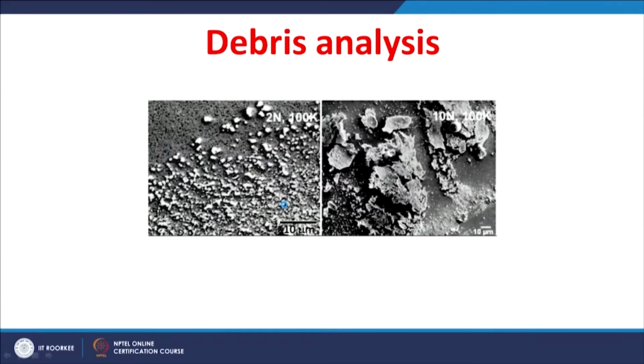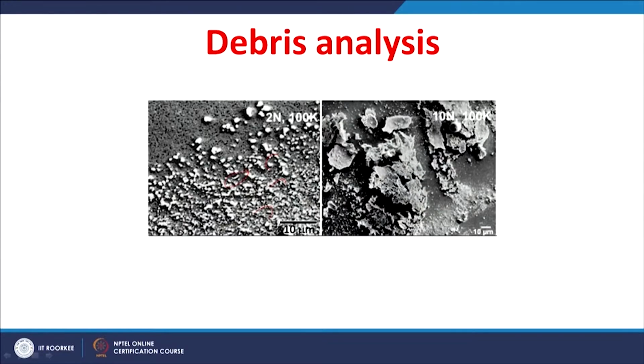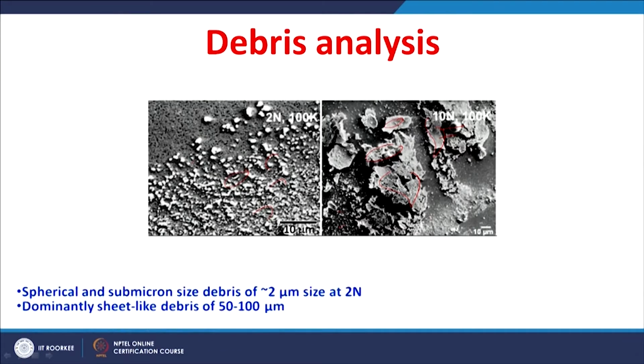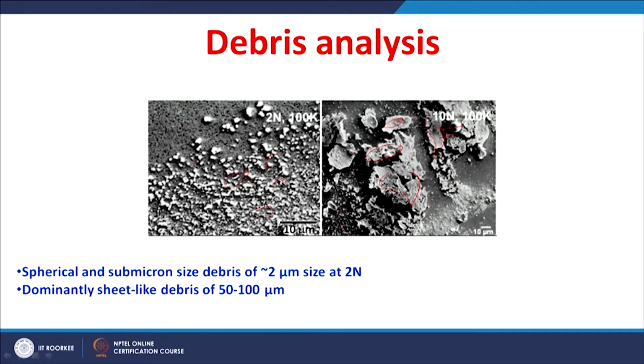So, the debris are also collected, and the debris analysis also shows a striking difference with respect to load. At the lower load you can see the debris of a very small size, whereas at the increased load of 10 Newton you can see that the debris are dominantly sheet like or plate like with a larger size. Of course, there is smaller debris here, but predominantly there is sheet like debris, around 50 to 100 micrometer, whereas the small debris observed after fretting at a lower load of 2 Newton is around 2 micrometer. So, there is a change in the size of the debris as well as the shape of the debris with respect to load.